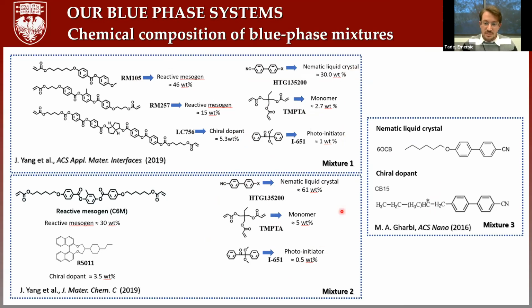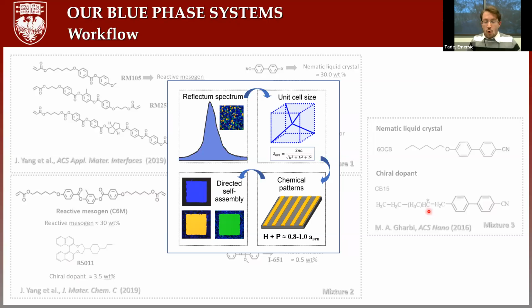Mixture 2 is similar to mixture 1, but here we have a higher percentage of the nematic liquid crystal. And then mixture 3 is pretty simple. We have the nematic liquid crystal and chiral dopant just in a ratio like 50-50. And so what does our workflow actually look like? So first, we take one of these mixtures. We create polydomains of the blue phase. And then we focus on one particular domain that we want to go into a single crystal later, right?